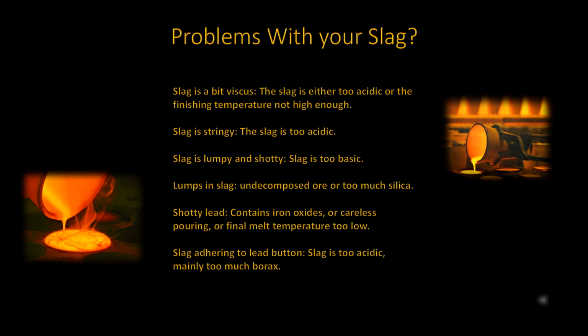A slag becomes stringy due to an increase in the slag's viscosity. It would be treated the same as a thicker slag. The reason is the slag being too acidic. On the other hand, if the slag showed some lumpiness and the shots were noticed breaking off during the pour, it would indicate that the slag was too basic. Increasing the acidic fluxes or decreasing the quantity of basic fluxes would resolve these problems.